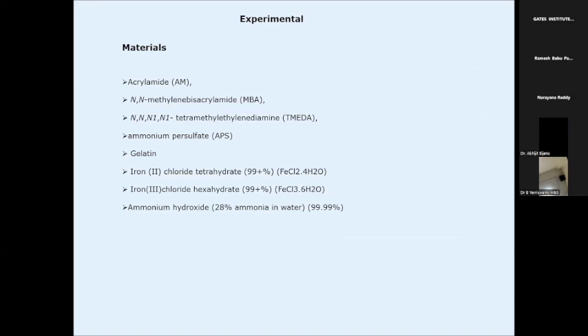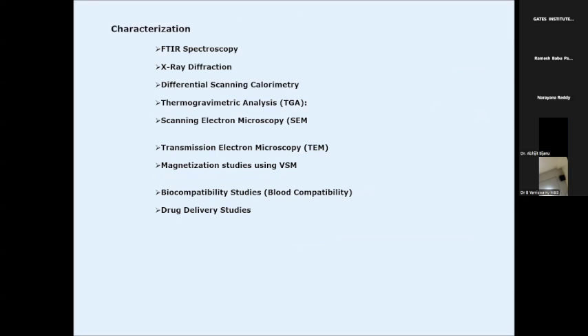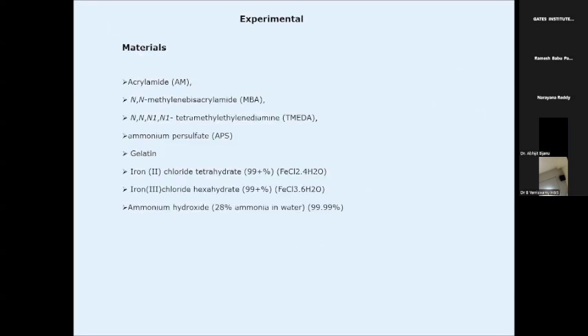So we have selected certain raw materials for this purpose. We have taken acrylamide chemistry, and methylene bisacrylamide. This is also one type of cross-linking system. So basically MBA acts as a cross-linking monomer. And then this TEMED is another catalyst system. Ammonium persulfate is a catalyst system. So gelatin, iron chloride tetrahydrate, iron chloride hexahydrate, ammonium hydroxide. These are the raw materials.